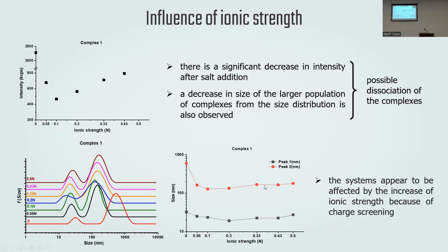To investigate the influence of ionic strength, we added a sodium chloride solution to the complexes, and we also investigated the behavior by dynamic light scattering. We can see here in the first figure a significant decrease in intensity after the salt addition, and we can see from the size distributions also a decrease in the size of the larger population of complexes. These results suggest a possible dissociation of the complexes.